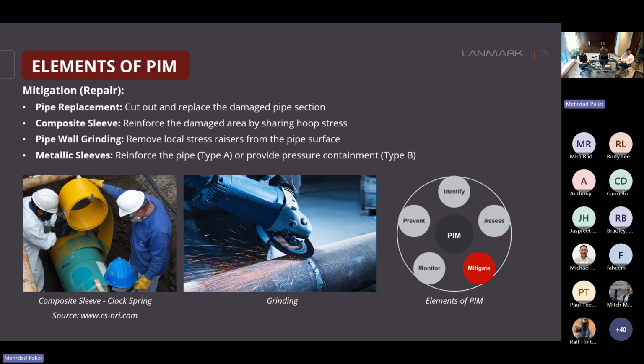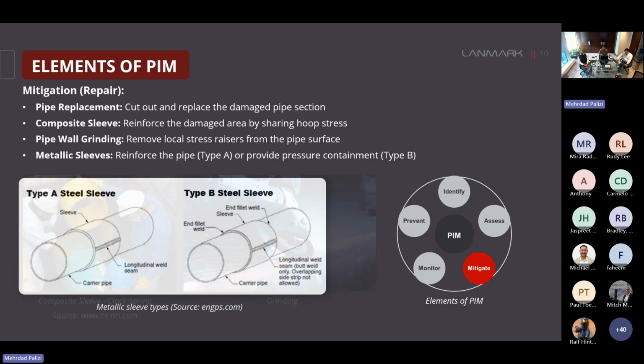Pipe replacement removes the damaged section of the pipe. However, this method requires line outage and it is not preferred. Composite sleeves reinforce the pipe by sharing the hoop stress, so they can be used for the longitudinal defects. Grinding basically removes the local stress risers over the pipe. And we also have metallic sleeves that are commonly available in two forms. Type A sleeves provide reinforcement, and in type B, we have the sleeve welded to the pipe. This type provides pressure containment, and it is generally used for more severe defects for which we might have leakage.